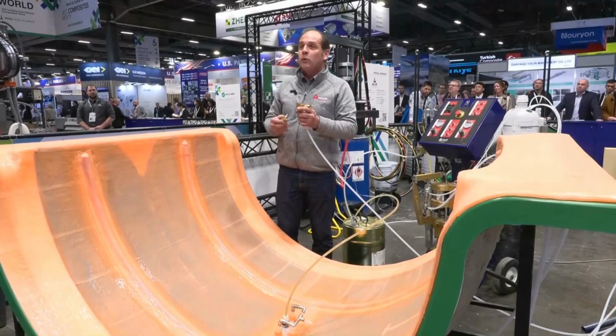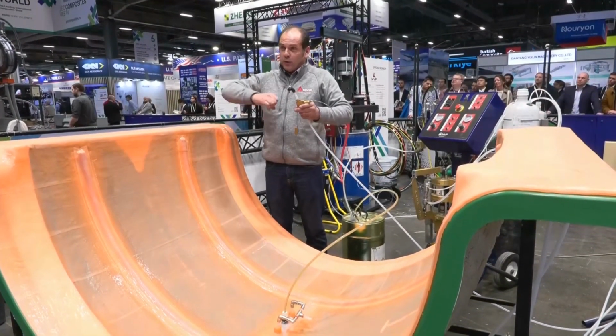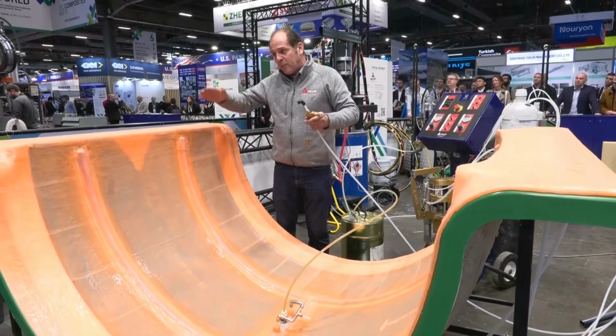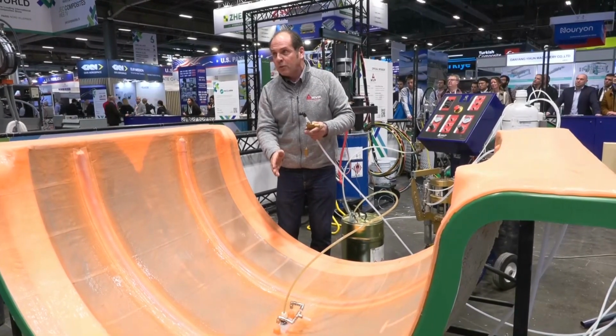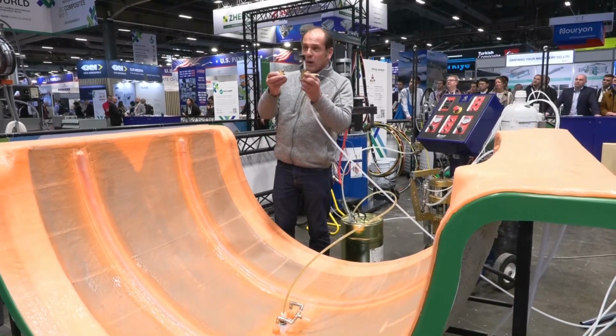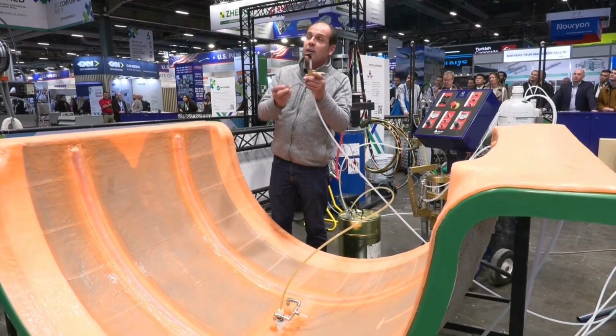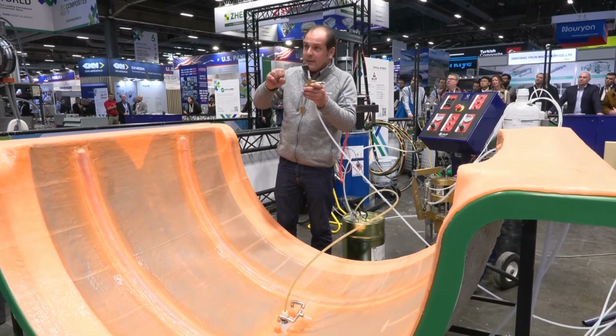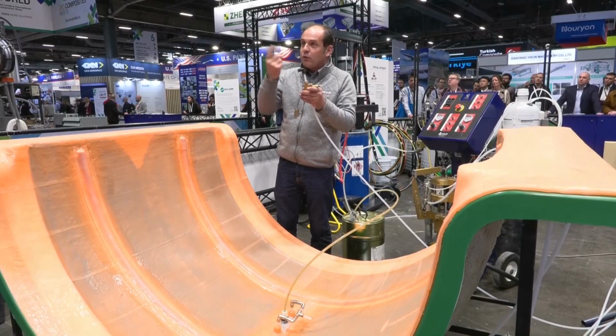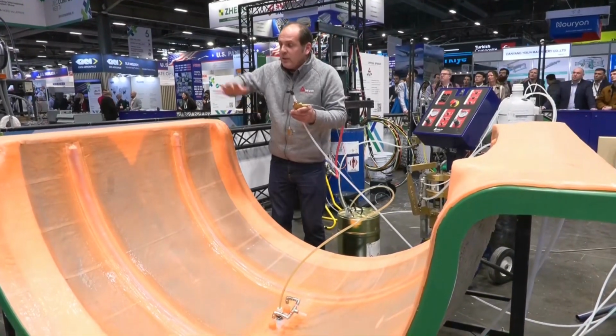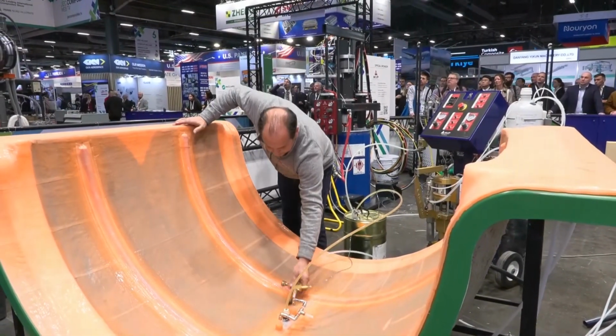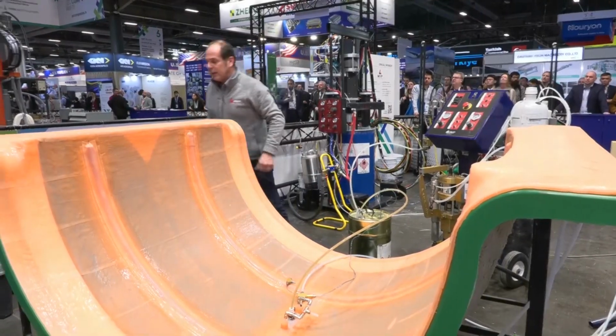If you stop the vacuum at once, the resin collapses, so it's a huge quantity of resin, and sometimes with gravity, that resin comes back into the middle of the part. So we calibrate the air coming in like that, so they collapse back in like 2 minutes instead of 2 seconds. So then the resin can flow up. So we leave it like that. Let's continue the presentation.